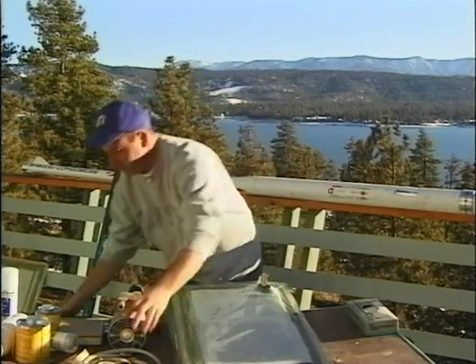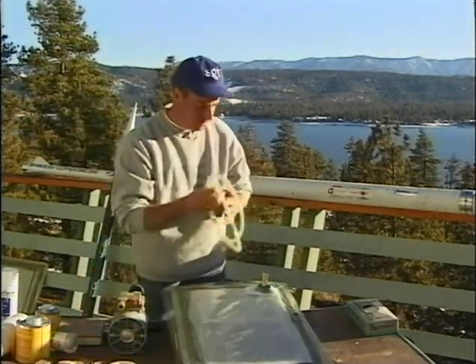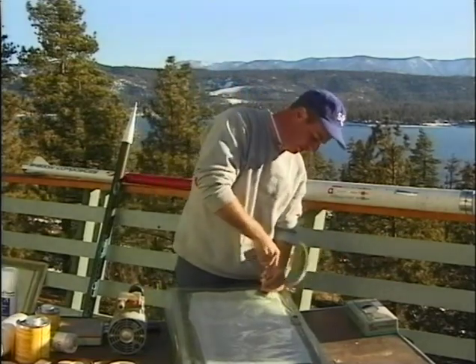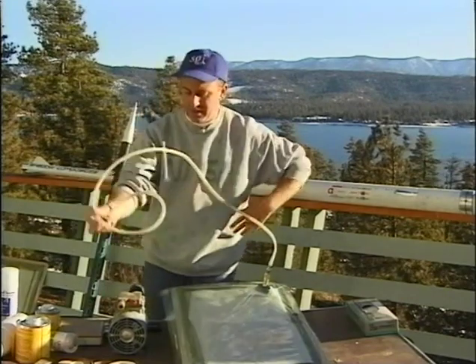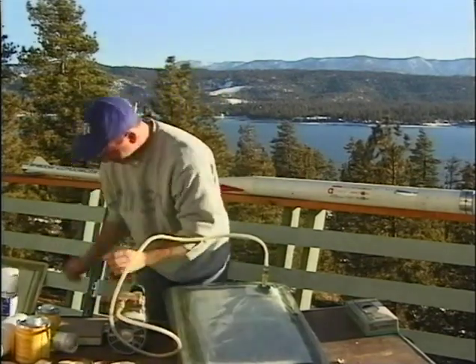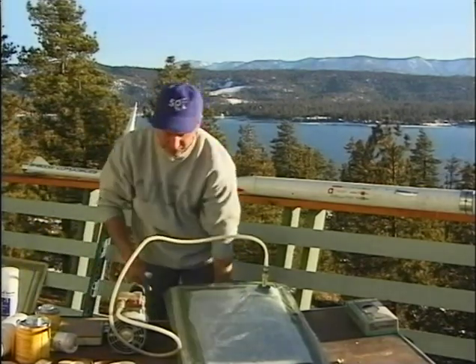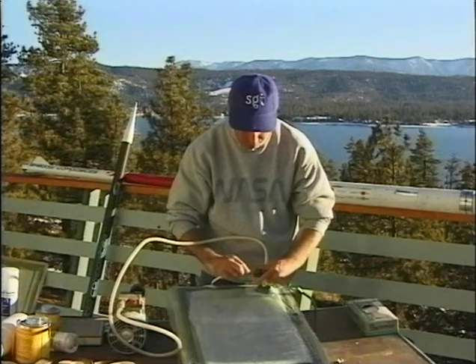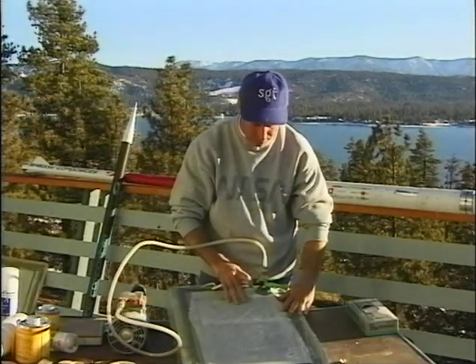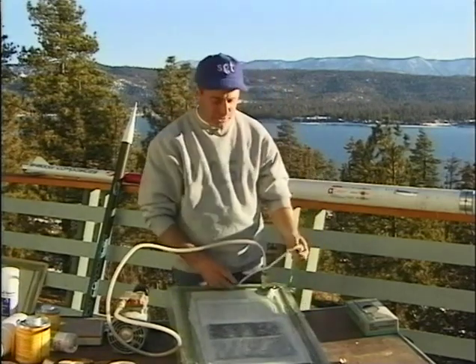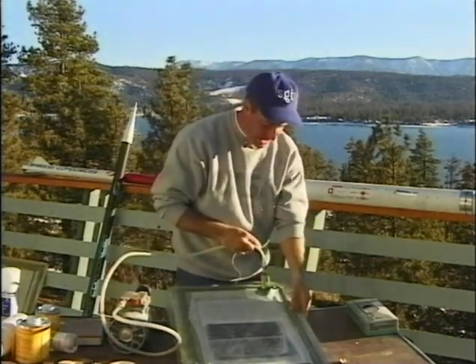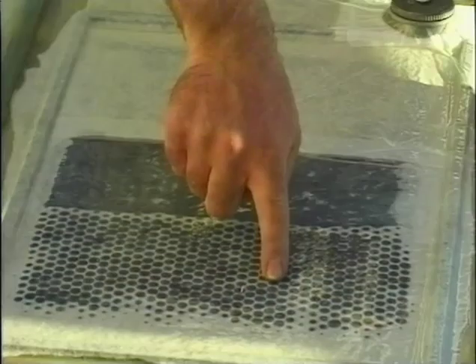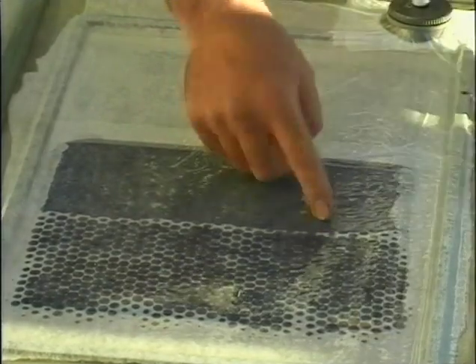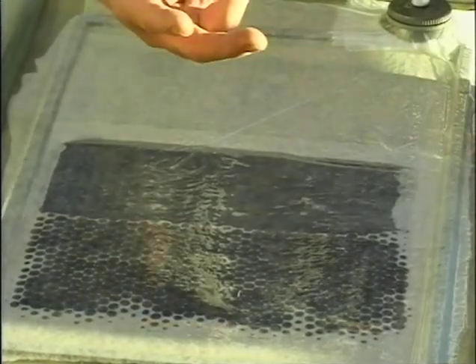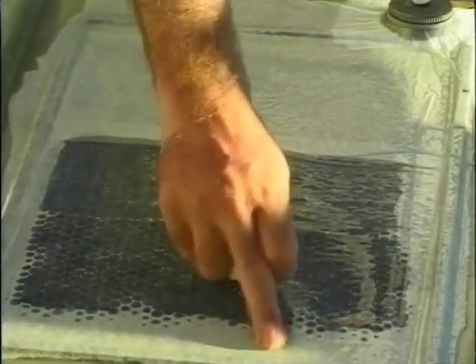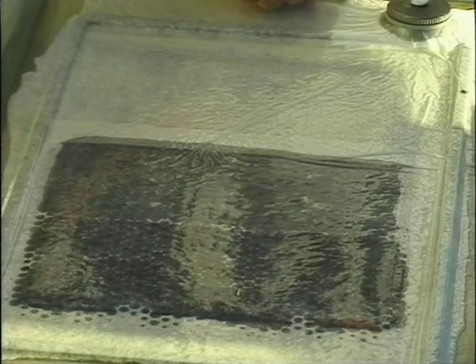Doesn't matter. Because now we're going to hook up the hose to the vacuum takeoff fixture. We're going to hook this in to our vacuum pump. And we're going to pull a vacuum on the part. Now, if you look closely, what you'll see is that in this area, there's little dark dots. That's where the resin is coming up through the perforated release layer and soaking into the breather cloth, right?